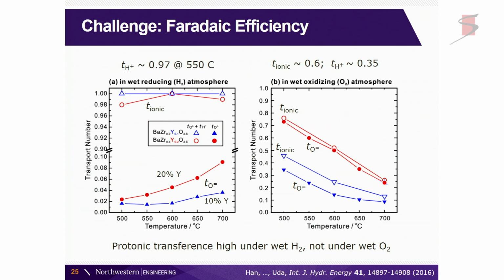Now, there is a challenge. And that is that there is a little bit of electronic leakage through this electrolyte. And it's not very much, so we have a 97% transference number for protons, so maybe about 2 or 3% transference number for electrons. And you think, okay, that's not so bad. But that's true in the reducing atmospheres. When you go to more oxidizing atmospheres, now the transference number of protons decreases. It's not terrible to have it be somewhat oxygen ion conducting, but it is a problem if it is electronically conducting, because that means that you're just losing some of your current towards just making heat, basically.